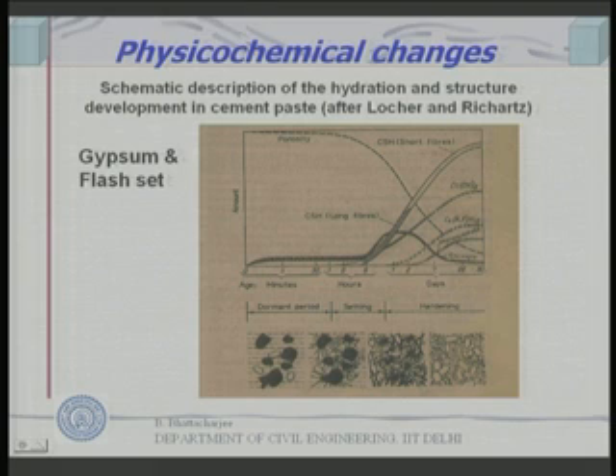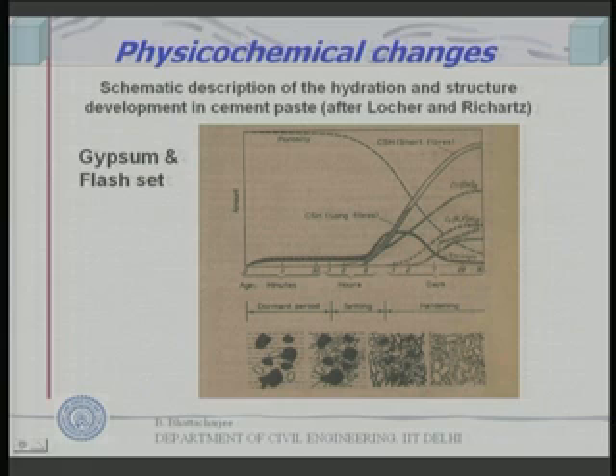So, in order to control this setting process, we add some amount of gypsum. Gypsum is calcium sulphate, and this calcium sulphate has high affinity for C3A, that is tricalcium aluminate. Tricalcium aluminate and gypsum react, forming calcium sulfoaluminates. The name of this compound is ettringite, right. That is the first thing that forms during the dormant period, and you can see the dormant period here.